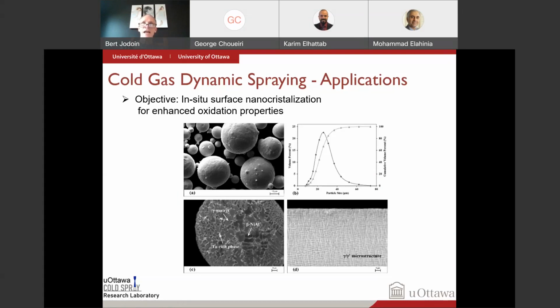And the idea here is actually to go a bit counterintuitive. What we've done is we've sprayed the coating using very, very poor spray parameters. The reason for that is we want to have a low deposition efficiency, to have only a few particles once in a while that stick, and lots of them bombarding them on top of it. By doing that, you're going to get so much bombardment that you're going to get a nanocrystalline coating produced in situ. So you start with regular cheap powder and it becomes nanocrystalline.